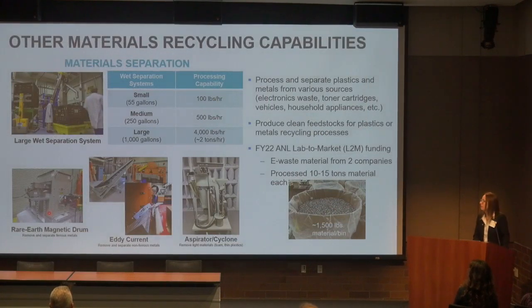We have other material recycling capabilities. A lot of this equipment was left over from, I shouldn't say a long time ago, but when Jeff originally started at Argonne National Lab, he was working in the recycling field and used some of this pilot scale equipment for other recycling purposes, such as electronic waste, toner cartridges, household appliances, et cetera. So we have large dry and wet separation systems that are capable of handling 100 pounds per hour to 4,000 pounds per hour. And then we have magnetic separation equipment, such as a rare earth magnetic drum for separating ferrous metals, eddy current separator for separating non-ferrous metals, and aspirator cyclone equipment for removing light materials such as your foam and thin plastics from your heavier, denser materials.